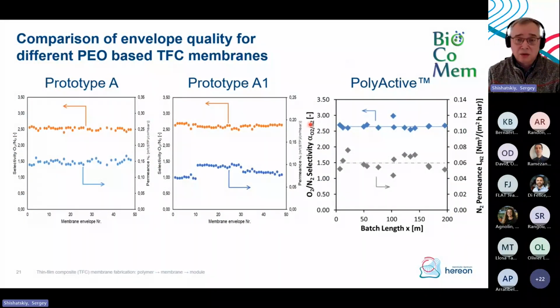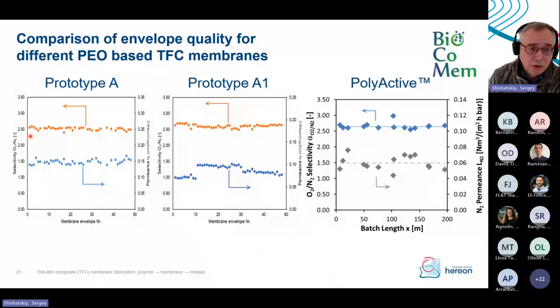Here you see results of testing of envelopes with respect to the number of the envelope, and this number is related to the position of the envelope along the membrane which was produced. And you can see that for prototypes A and A1, the selectivity for oxygen nitrogen was quite constant. In the case of prototype A1, the permeance of nitrogen jumped. I think it's due to a change of the speed of one roller. And then it slightly decayed to the end. That's most probably due to evaporation of solvent from the bath from which a roller picks up polymer solution, and so we get a thicker layer.